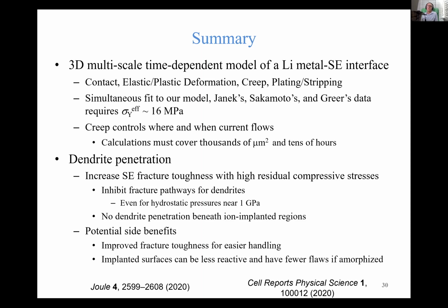In the first place, these materials are extremely brittle, and it's going to be a challenge to handle them in a factory environment. Of course, if they have improved fracture toughness, then they don't break as often. The other idea is that if you're doing implantation, you tend to amorphize the surface, and amorphous surfaces often may have fewer flaws and therefore be less reactive, and that may make it less important to have, for example, chemical interlayers. So that's the end of the technical talk.